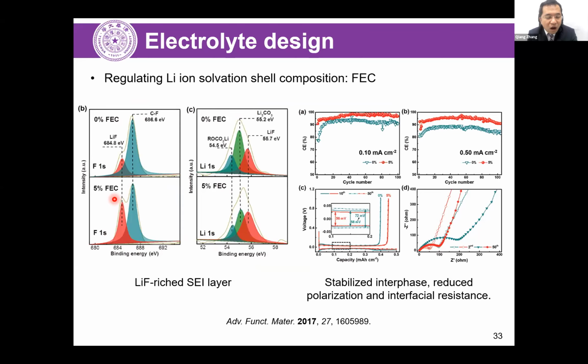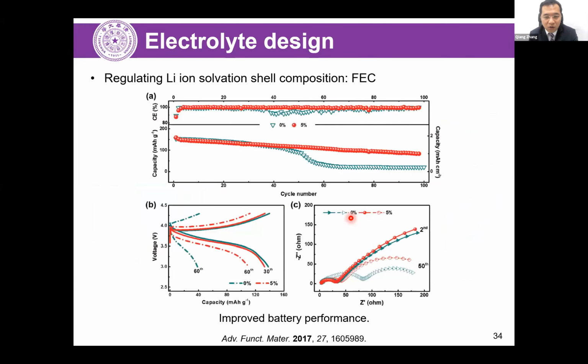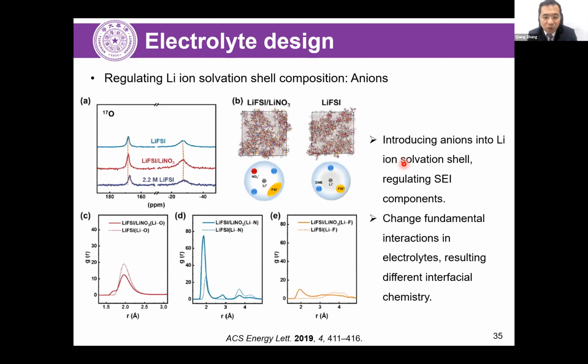So in this case, the introduction of FEC provides a uniform, highly ion conductive but electron-rejecting layer of SEI, and this guarantees the Coulombic efficiency of the lithium metal anodes was quite high, and the polarization on the interface was small and relatively stable. So this is quite important for working cells, rendering the full cell of lithium metal paired with NCM, nickel cobalt manganese oxide, with stable cycling. So in this case, it is found that the electrolyte additive can regulate the lithium-ion solvation structure, and this helps the stable SEI formation.